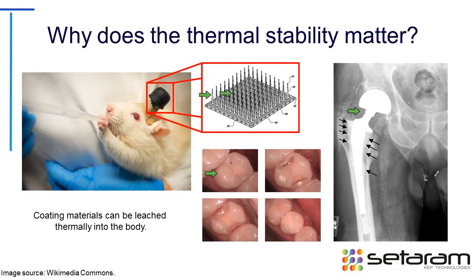In the case of the Utah array, we don't want whatever coating that we're going to be putting onto the Utah array and the polymers for it to degrade and leach out into the brain. In the case of dental implants, we don't want you to drink coffee and then the polymer coating on your teeth ends up just degrading and causing toxicology issues, or be it with friction occurring in artificial joints. We don't want polymer coatings or other protein-type coatings to leach out and cause toxicology issues, or for them to degrade and have minimal performance in the case of protein.